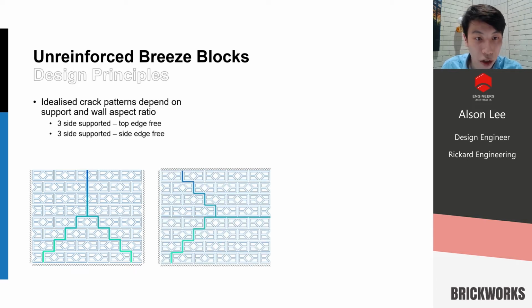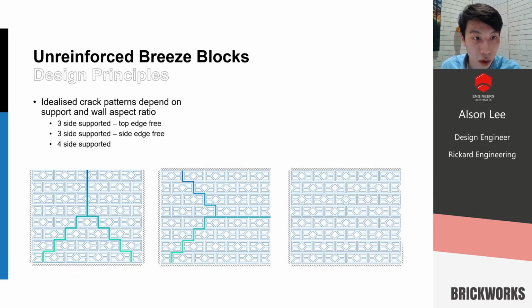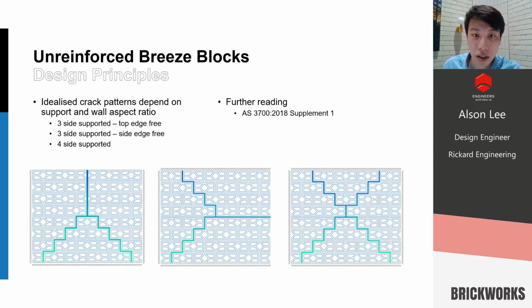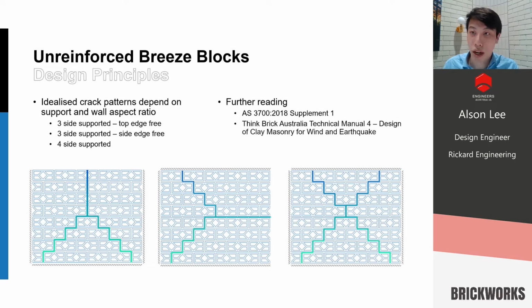A similar failure pattern can be observed when the side edge is free. So imagine you've rotated it by 90 degrees. The asymmetry here is due to the slightly asymmetric nature of our blockwork example, but these are idealized crack patterns, just to show the idea of failure, or what we expect. And finally, 4 side supported will exhibit almost fully diagonal cracking patterns depending on our wall aspect ratio. For those who are interested, there is great further reading in the 3700 Supplement 1, which details research and the virtual work method, and also in the Think Brick technical manuals, which are a fantastic resource with many examples and technical information.